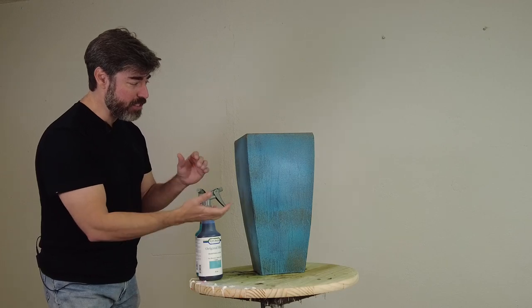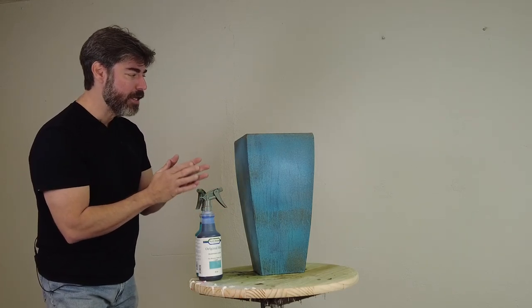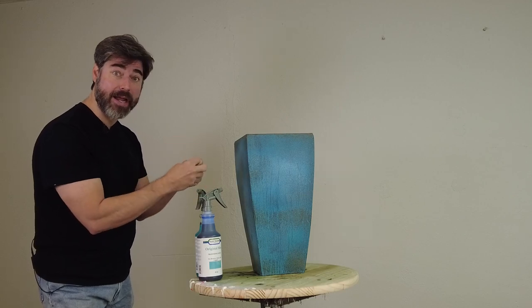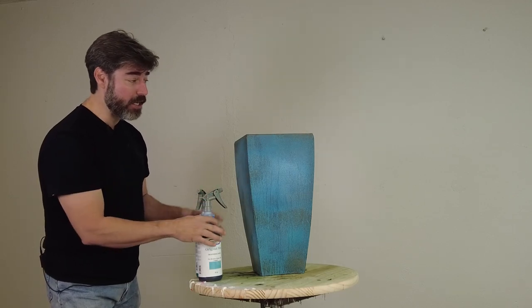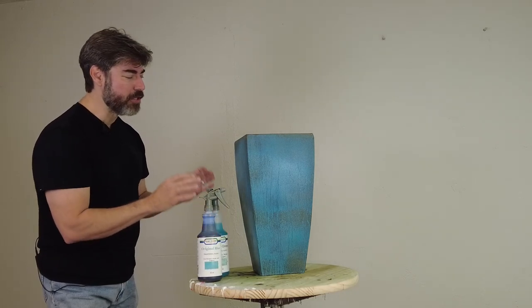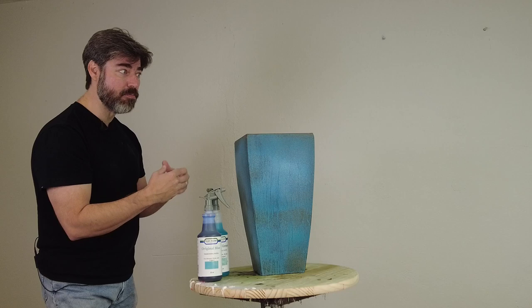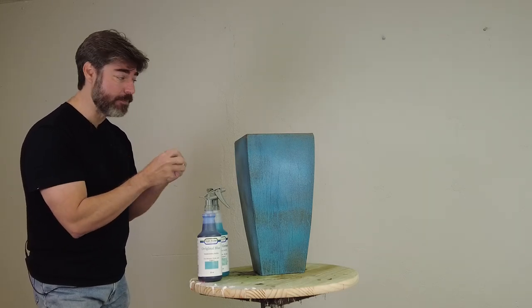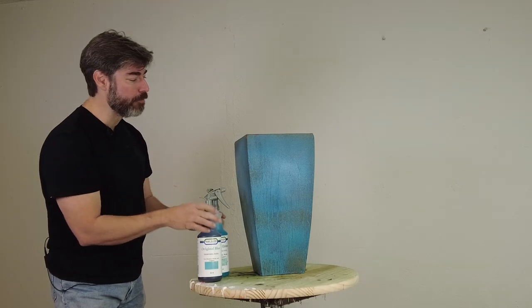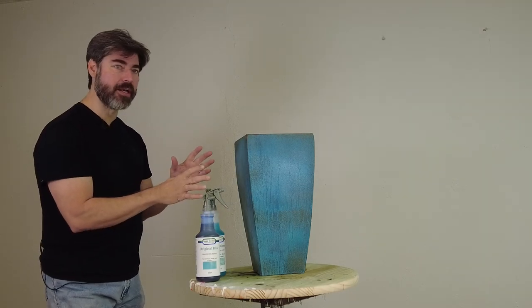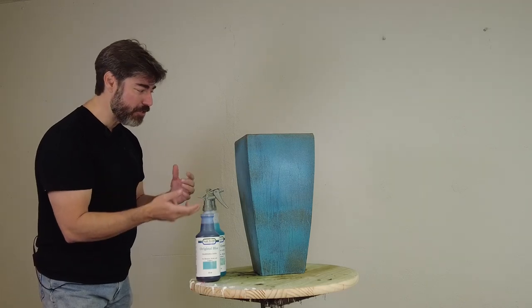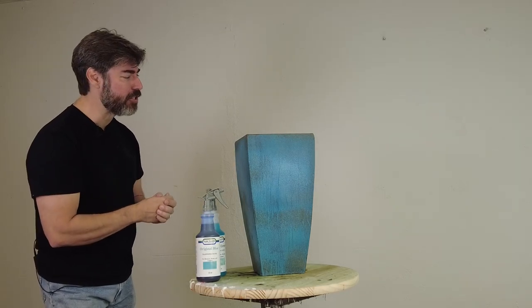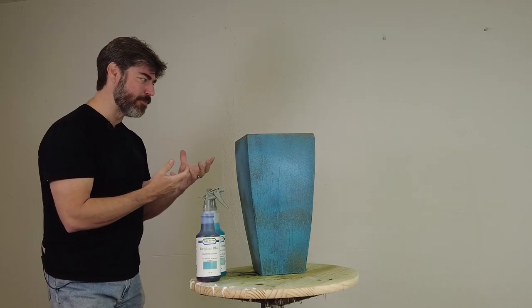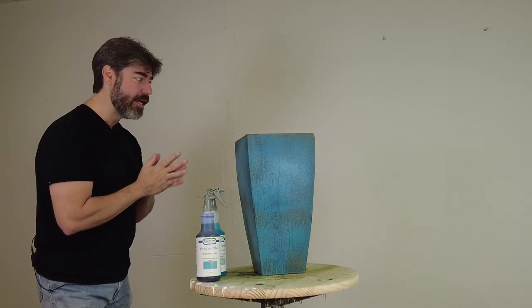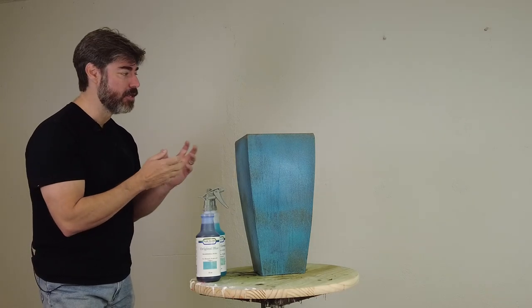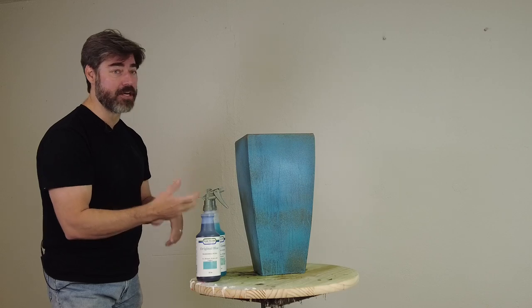And what's happening here is two different things are happening. The acrylic is drying around that copper, and at the same time, we're getting a reaction from these patinas. So there's kind of a race where you want as much of a reaction to happen before that acrylic locks in that metal powder. So this is another reason why you want to work in an area where things don't dry too fast, so that it locks that in and turns off that reaction. And a lot of times when you're getting a really poor patina reaction, it's because it's too hot and too dry, because the metal coating is drying too fast to get a really good reaction.